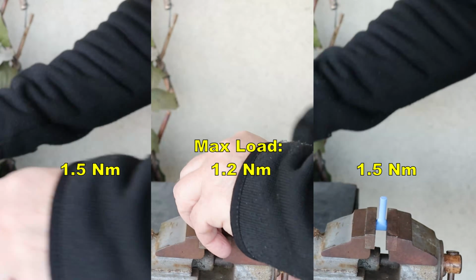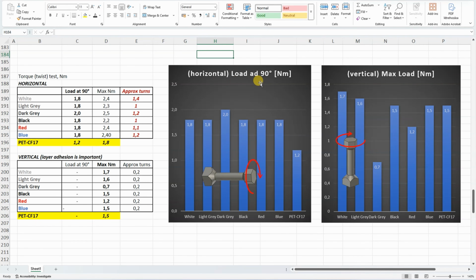1.5. Printed in horizontal position, loaded 90-degree rotation, more or less around 1.8 Newton meters, which is a bigger value compared to the carbon fiber version. Printed in vertical position, layer adhesion is important, and you can see more or less very similar values, around 1.5 Newton meters. I'm not sure what happened here with the dark gray. I'm quite sure this is some kind of error, but I don't have time to repeat it now. Probably during the holidays I will reprint this and repeat the test, and that summary pattern table will be updated later.